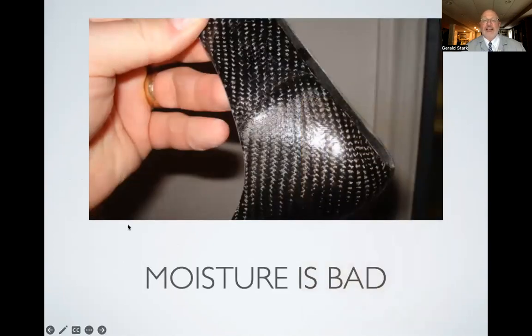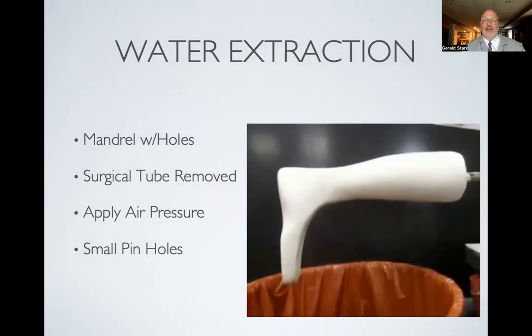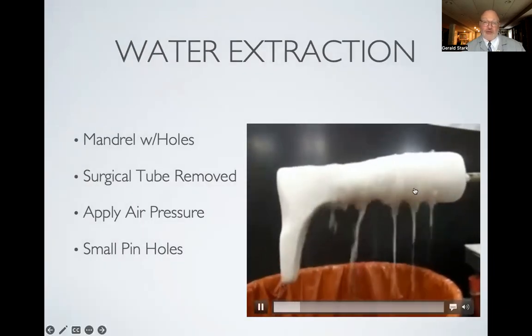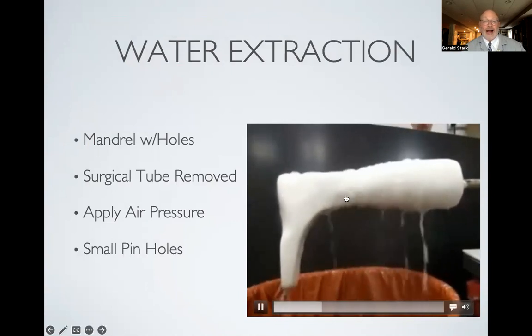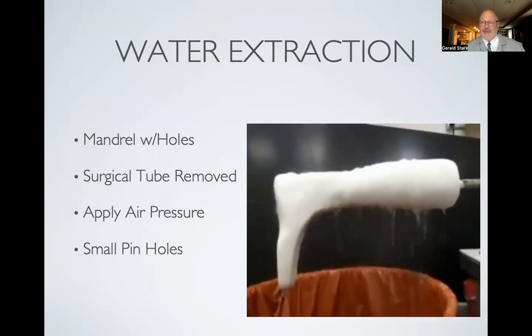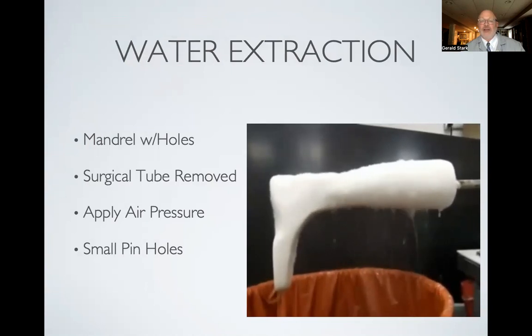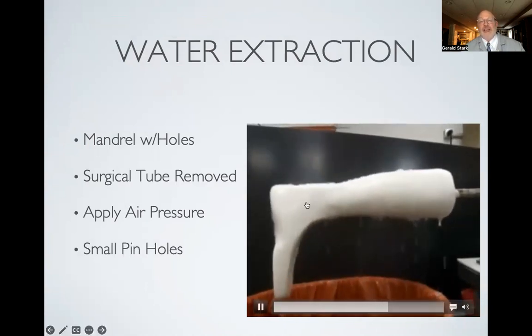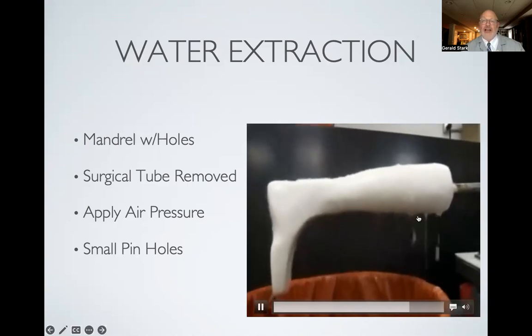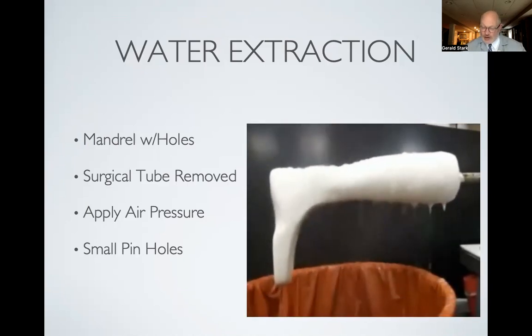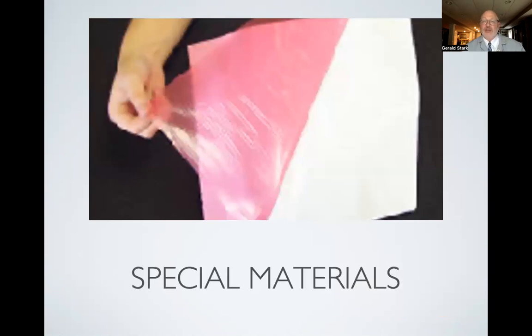Moisture is bad. Here you can see where a composite was exposed to moisture, and what it does is it steams the matrix. And so when it steams the matrix, you get some of this porosity, and this is where things can be broken over time with fatigue strength. Here's where you can actually create a mandrel with multiple holes, and you can blow the water out to remove as much water as you can. So it does create these micropores within the plaster, but if you coat it with a separating balloon, it should work quite well. And then using special materials, like you can't use the same old PVA bag you utilize.